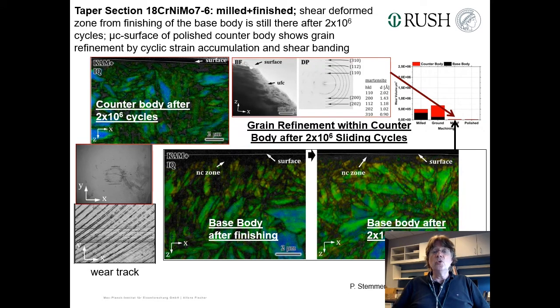If you finish the surface, you still see the milled rough surface, but the peaks are taken away. Again, this is the counterbody. We were not able to measure anywhere the same coefficient of friction, just to mention that. We knew this is roughly mild wear, this is ultra mild wear, where we would like to go. So this is a surface after the fabrication process with the strains.